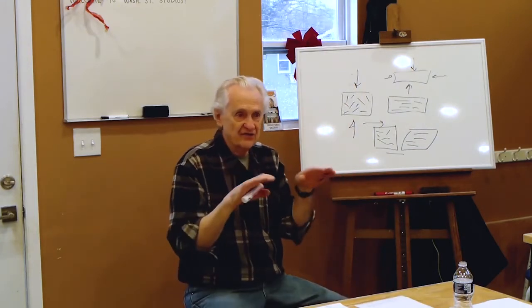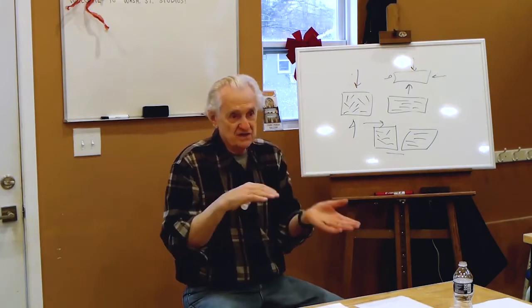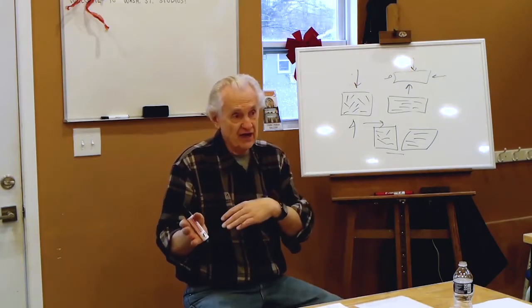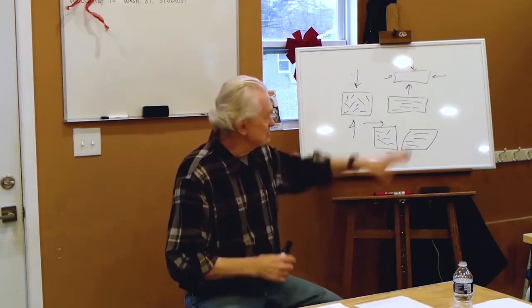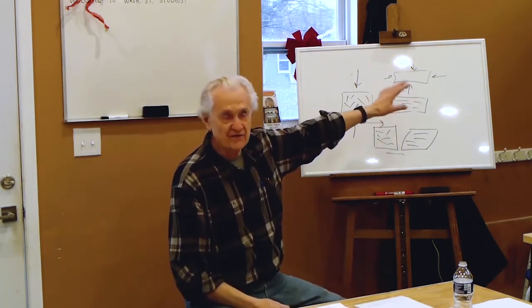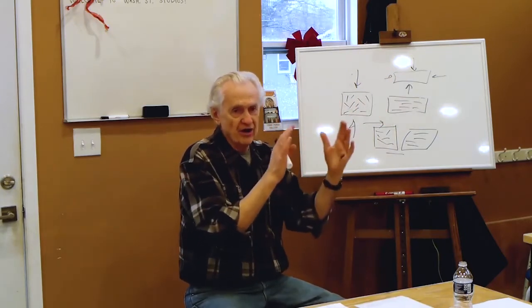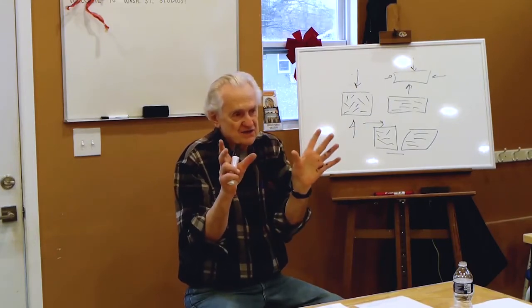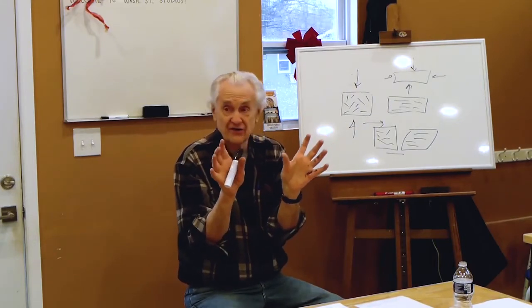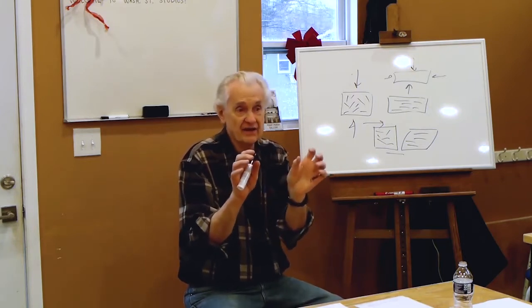They don't behave the same in all directions. So when the particles are oriented in one direction versus the other, the shrinkage is different, in both the drying and the firing. This is one of the major causes of drying cracks and a lot of other problems: differences in orientation. If the particles in one part of a pot are oriented differently than those in another part, that means the shrinkages between those two parts are different. Well, if the shrinkage is different enough, you get cracks.